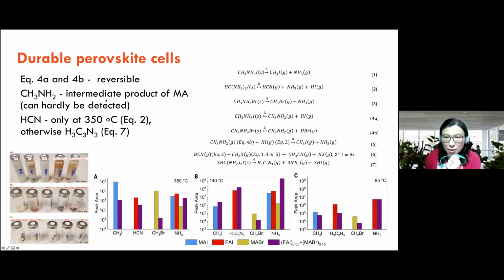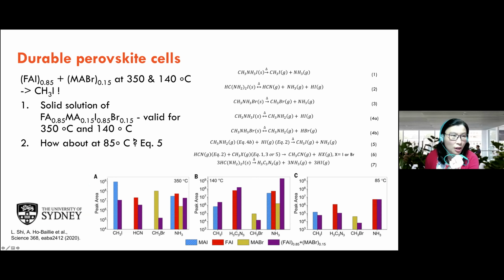So what we see is for MAI, the signature product is CH3I. For the FAI, the signature product is HCN at high temperature, and fortunately, at low temperature, it is not hydrogen cyanide. For MABr, we get CH3Br. And for the mixture, you'll have the combination of both, and I'll explain a bit later. So from these signature products, we can arrive at the decomposition reactions of equations 1, 2, 3, and 4, where equation 4 is reversible. We also have the CH3NH2 product, the intermediate product of MA, but it can hardly be detected. And again, HCN is detected at high temperature, but not at low temperature.